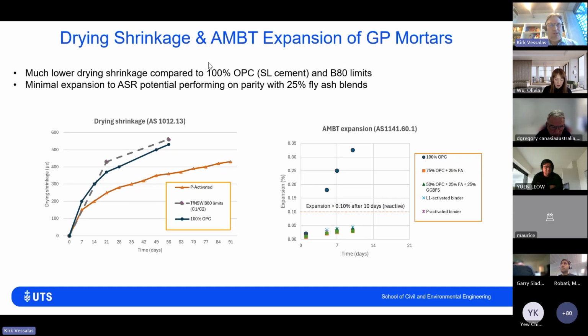Just moving forward with a few other results, an example of some of the results that we have here is volume stability, looking at drying shrinkage. I've incorporated Transport for New South Wales B80 limits, which is the Bridges specification for concrete works. And you will see that for a conventional 100% ordinary Portland cement system, we're somewhere close to the limits, but when we look at a powder activated system, we're actually getting a little bit less drying shrinkage overall, again, over a number of weeks.